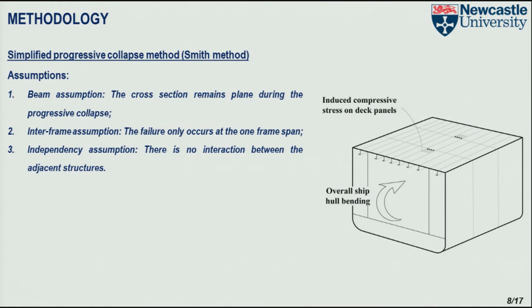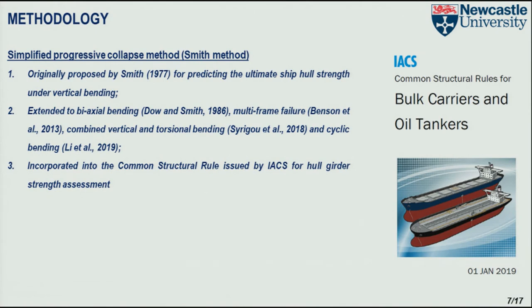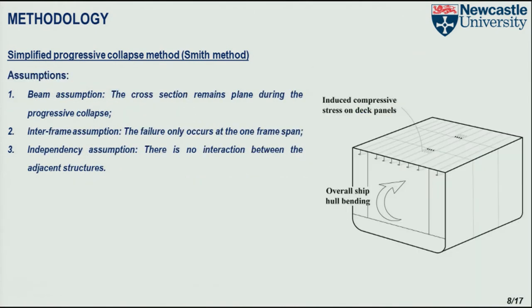First, we will subdivide the cross-section into structural elements like stiffened panel elements or hard corner elements. Stiffened panel element means that we will consider the buckling failure of the element. Hard corner element means the behavior of a hard corner element is elastic, perfectly plastic. Those are normally elements at the intersection between different plating. And the second step is we will assign a load shortening curve to each structural element. This load shortening curve represents and characterizes the behavior of the structural element under in-plane compression and tension, which are induced from the overall bending of the hull girder.